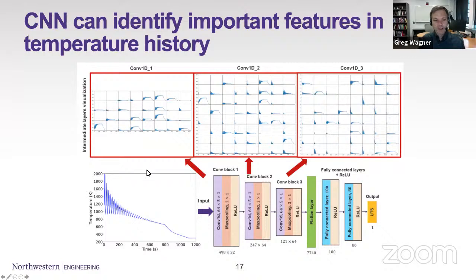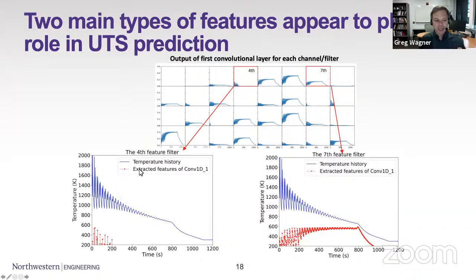Okay, and so we can look at these individual features in the CNN and again see what it is that this network is picking out and relating to the UTS. If we zoom in on a couple of these, there are really two classes of features that seem to be pulled out of this. The first, labeled fourth here, is something that is important at these early times when this material is in the melting range. So there's clearly something important about this solidification range, which is not surprising.